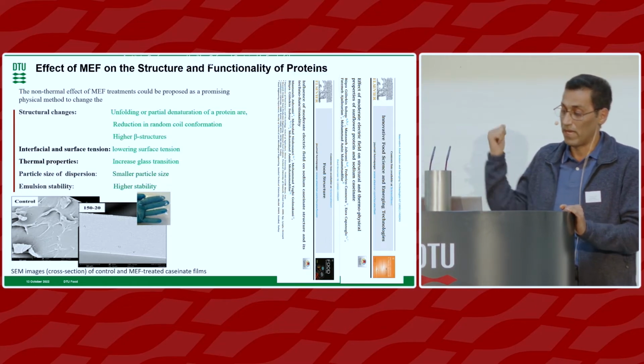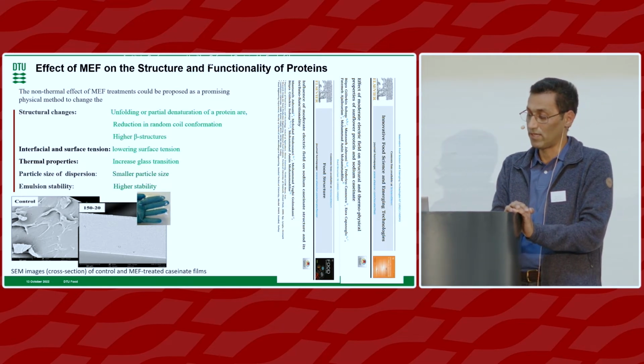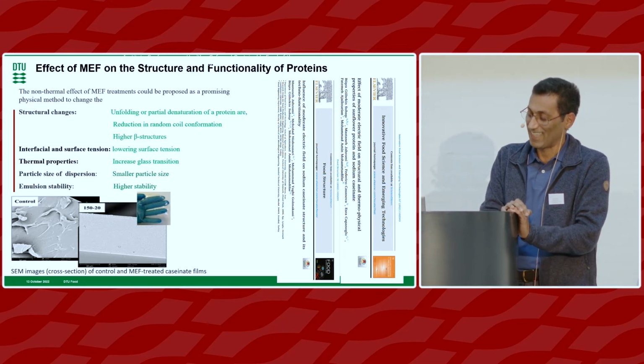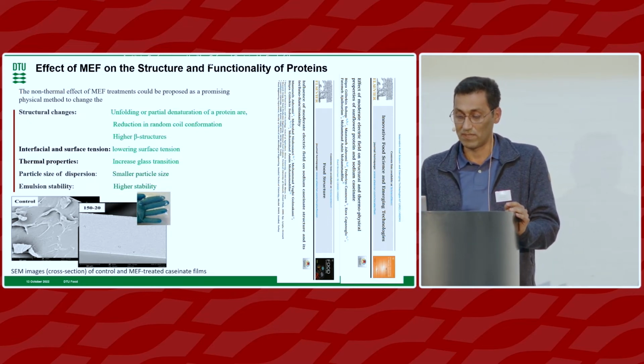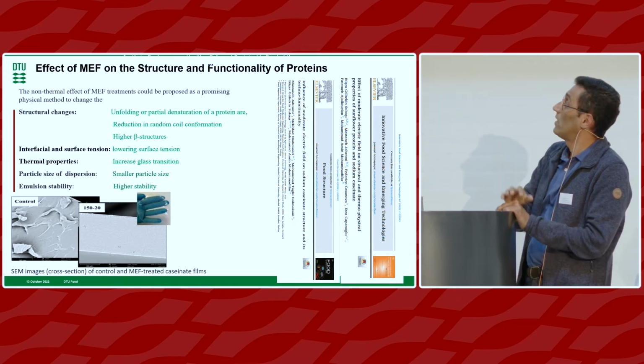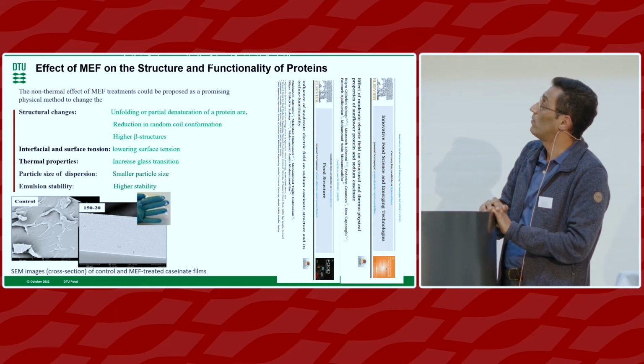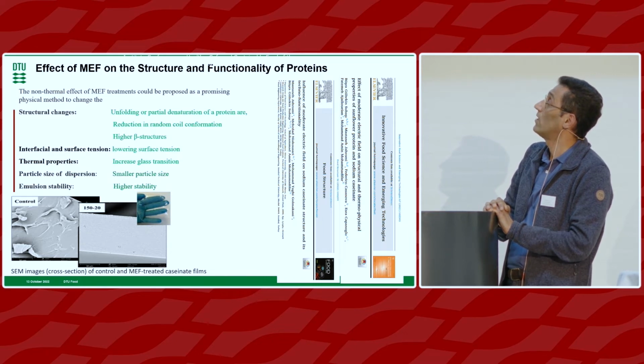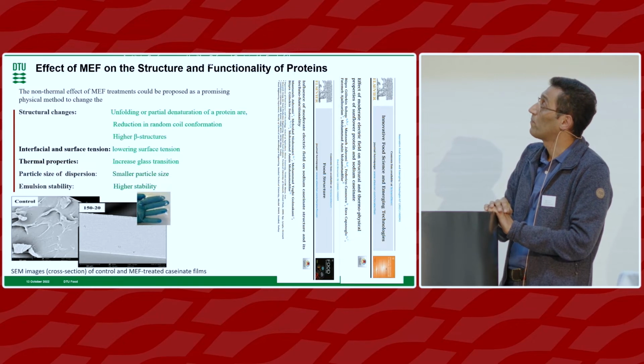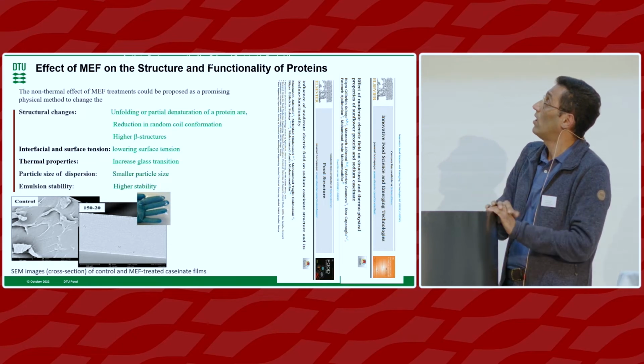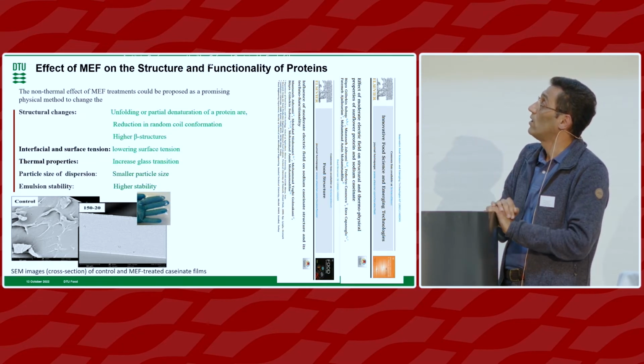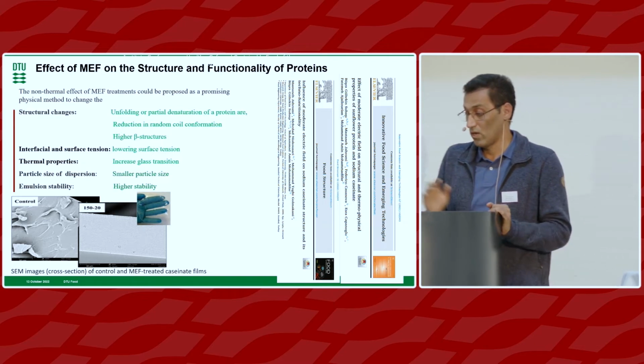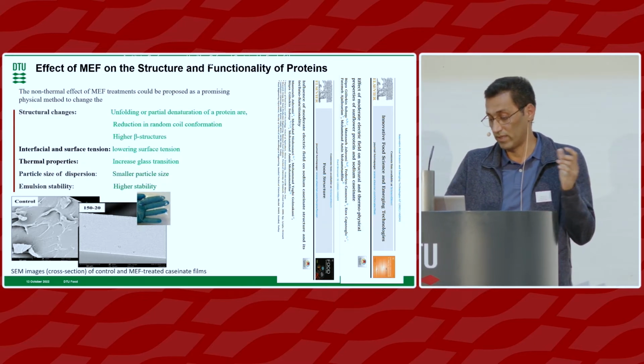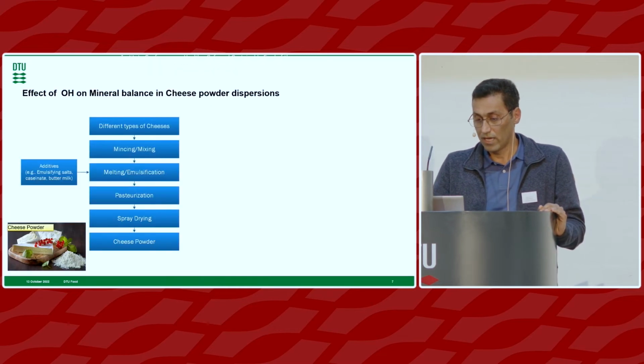And then we ended up making some edible films with electric field treated samples and control samples. You can see these are SEM, these are cross-sections of these edible films, and you can see the structure is completely uniform when you use the electric field treated samples compared to the control. And then we measured the mechanical properties of these films. We had a higher structural strength, and also at the same time we had more stretchability, which are desired quality attributes for edible films.